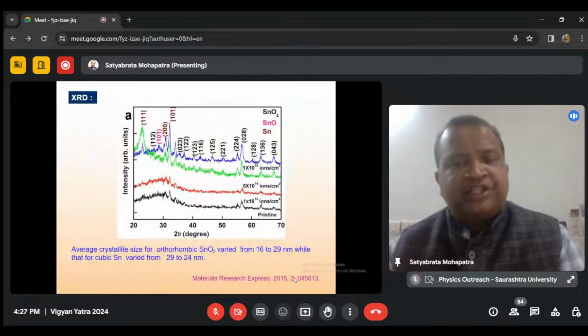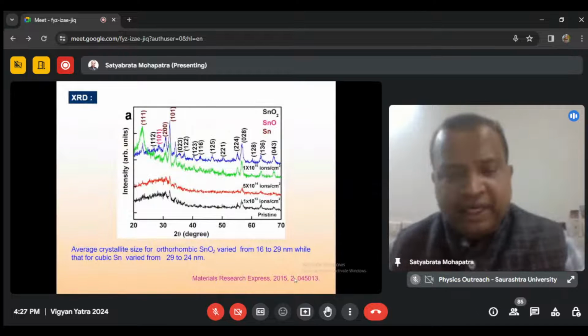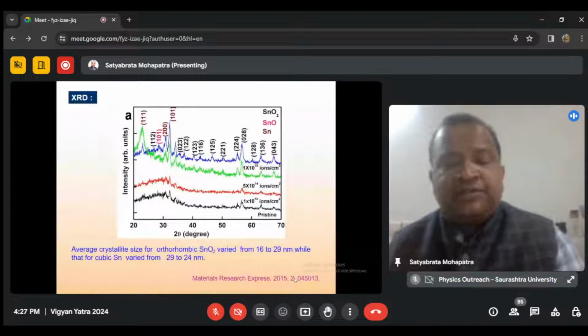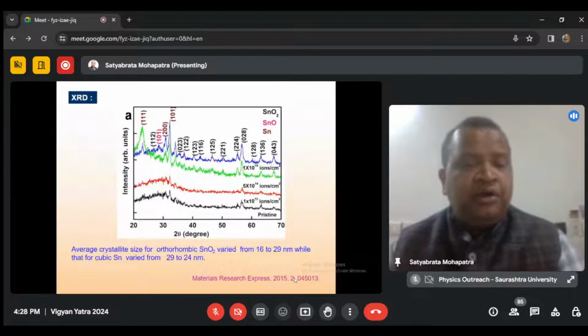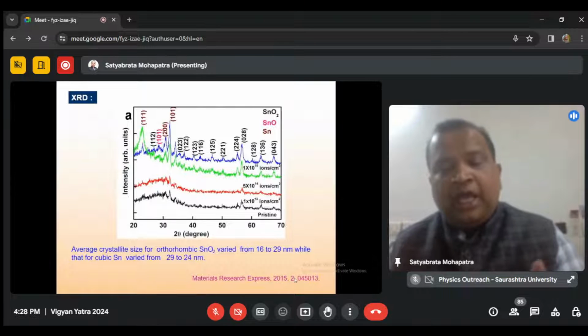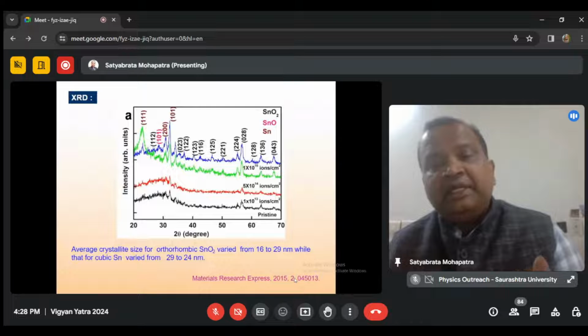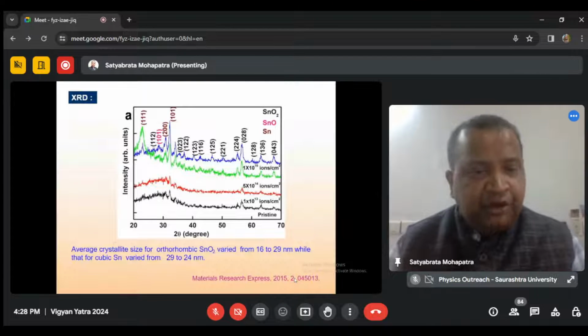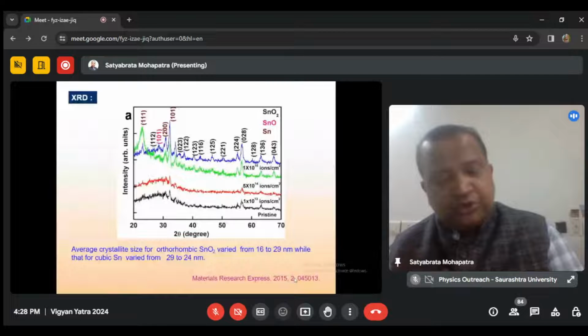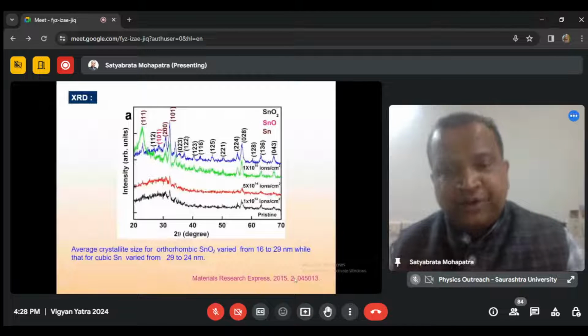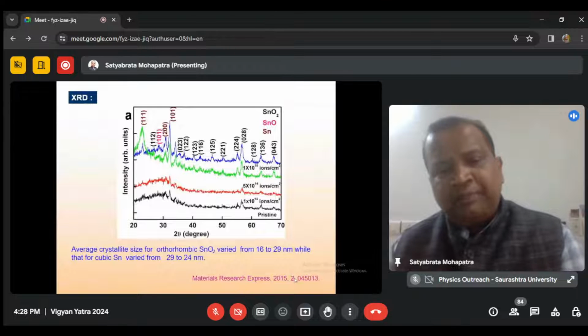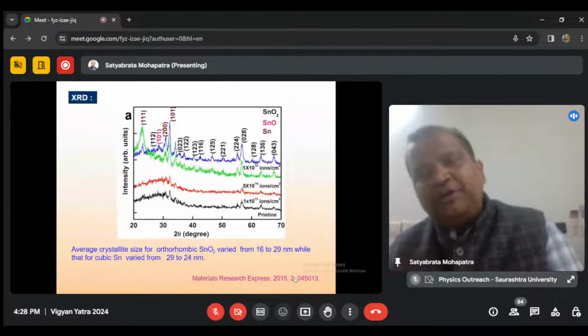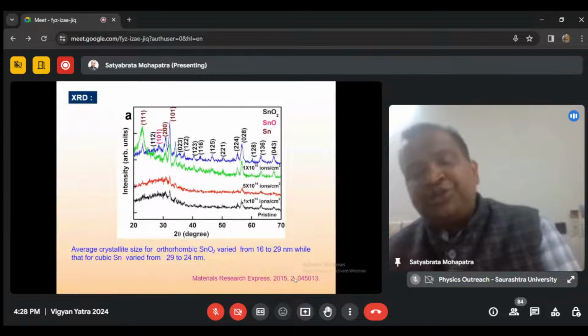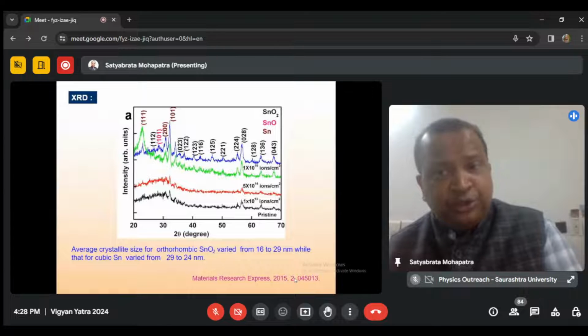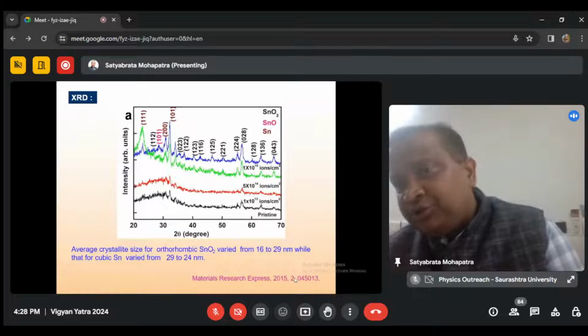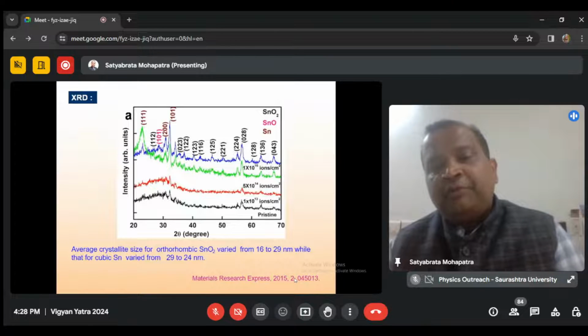Now the XRD patterns clearly show orthorhombic tin oxide, and there is an increase in crystallite size of tin oxide from 16 to 29 nanometer, whereas that for cubic tin varied from 29 to 24 nanometer. I want to emphasize that we deliberately created a tin and tin oxide combination by carbothermal reduction, because tin and tin oxide is a metal semiconductor heterojunction, which is beneficial for developing improved gas sensors. When a metal particle comes in contact with the semiconductor, depending on the work function of the metal, there will be a favorable situation where you can have improvement in gas sensor response. So we want to use this to our advantage, and on top of that, we wanted to use the ion beam to improve further their gas sensor response.